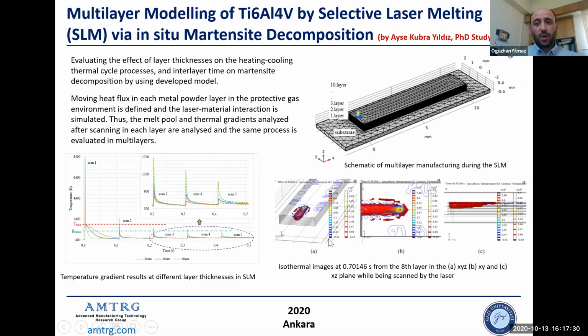Again, we are working on developing a model by using software like COMSOL, and then we predict the thermal gradients and the cooling rates, and what is going to happen after the process, especially for titanium 6-4. Can we reach the martensite transformation, and what could be the effect of layer thickness on this martensite decomposition, considering the heating and the cooling rates? Again, this is under research. She is continuing her PhD, and these are basically the first results of her study.